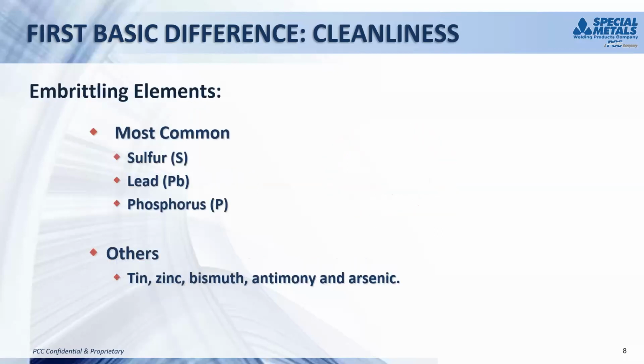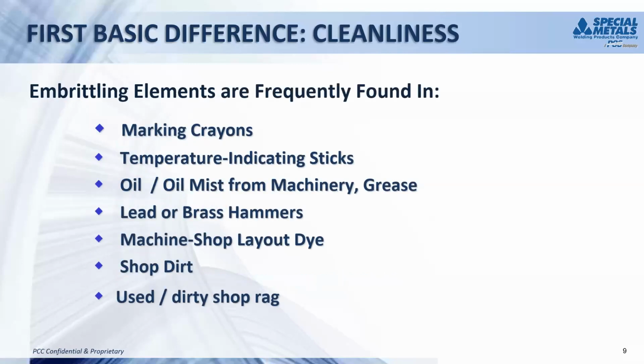Second one is embrittling elements, and the most commonly encountered are sulfur, lead, and phosphorus. But there's plenty of others: tin, zinc, bismuth, antimony, and arsenic. The "and" doesn't mean that arsenic is the last one. There's plenty of others. So just need to watch out for foreign materials that might be on your plate before you start to weld. John?